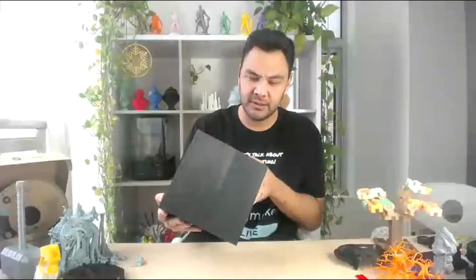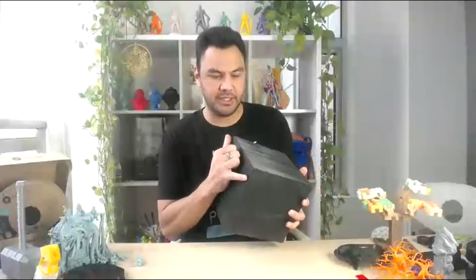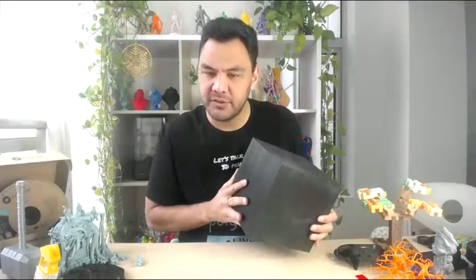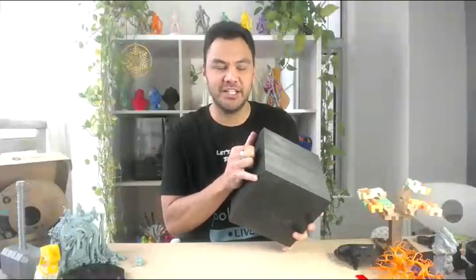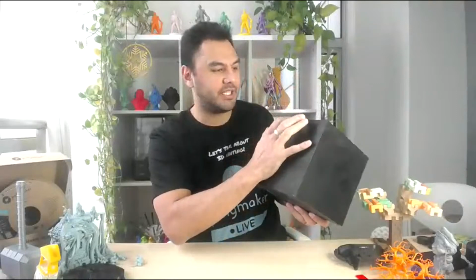It's 100% infill. I'm not sure, but I would say a good 2 to 3 days, if not more. It's about 25 centimeters by 25. If there are people from the US, I have no idea how many inches, but yeah, that's my hand. I have a big hand, but yeah, 25 centimeters by 25 centimeters, 100% infill, 0.2 layer height, and the extrusion width was 0.4. We used just the default profile, default setup, 0.4 nozzle. And what else do we have?